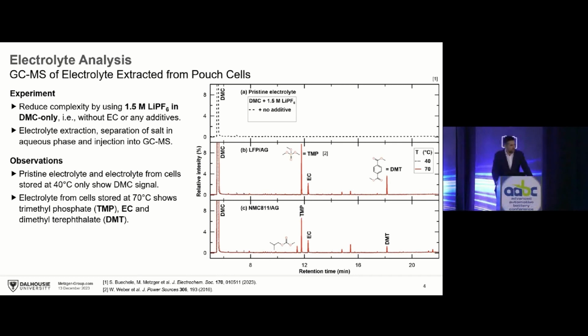Then, to our surprise, we also found ethylene carbonate here. But remember, we did not add that to the electrolyte, right? So ethylene carbonate has been formed. And then the other molecule that we were really intrigued by is the molecule at about 18 minutes retention time, which I labeled DMT. That stands for dimethyl terephthalate. So that is a very unusual molecule, right? It has a benzene ring. How could that possibly be formed in our battery cells if we only have our linear carbonate as the electrolyte solvent? So we were very intrigued by this molecule.